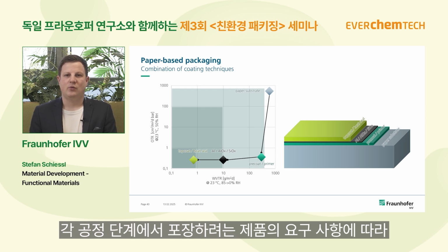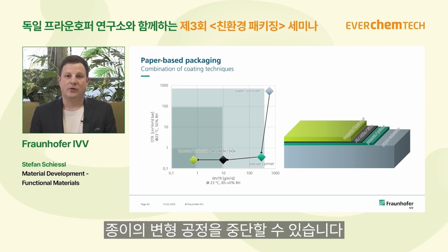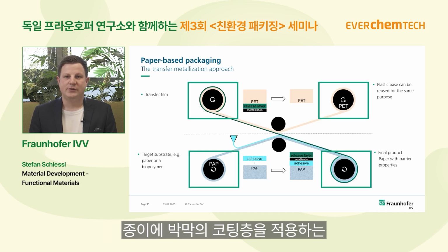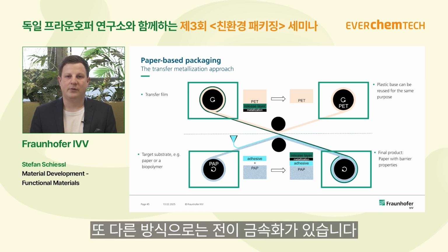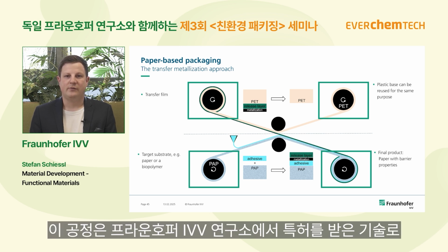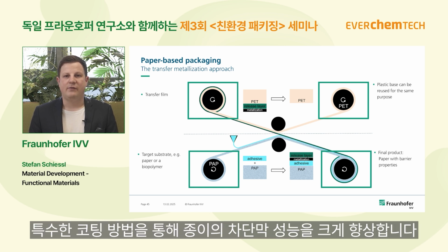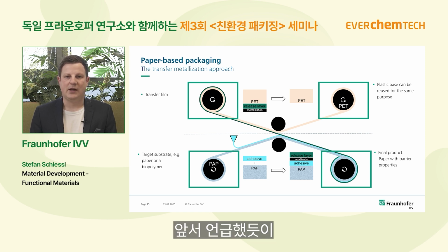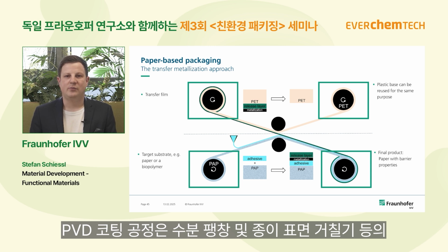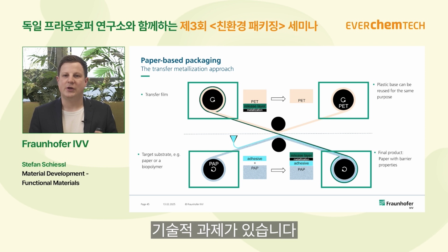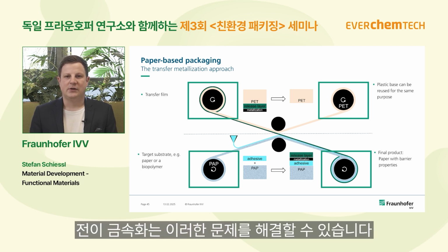So at each process step we are talking about, you can stop the modification of paper depending on the demand you have for the packed good. One other possibility to apply a very thin coating layer on paper is the transfer metallization. This process is patented by the Fraunhofer IVV and helps to create very good barrier properties on paper by the following process. As said, there are some challenges to do the PVD process on paper, like the hygroexpansion and the roughness, etc. This is neglected by the process that I will introduce now.